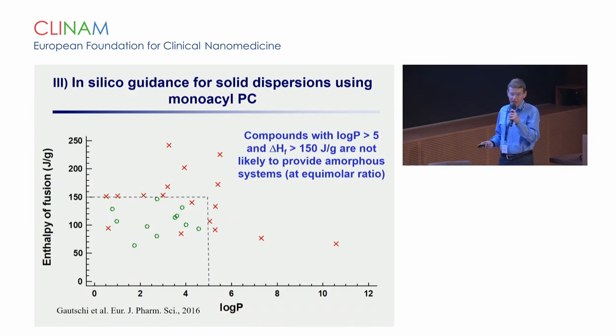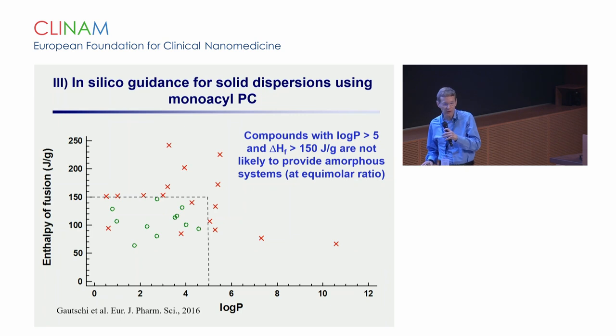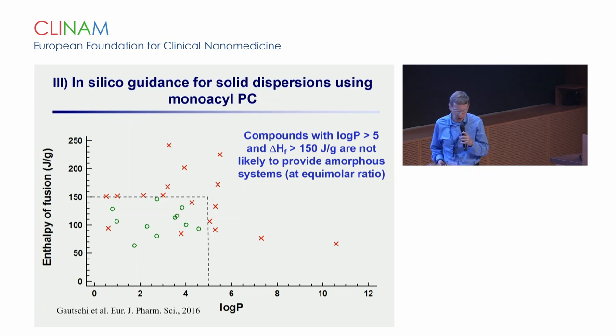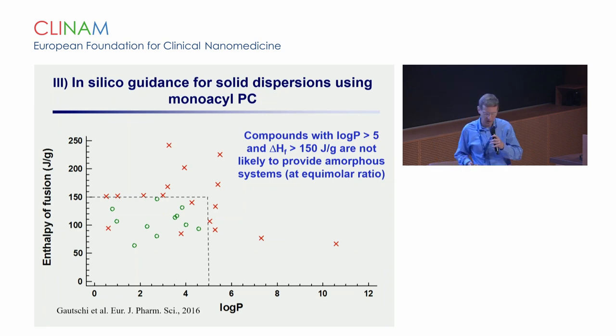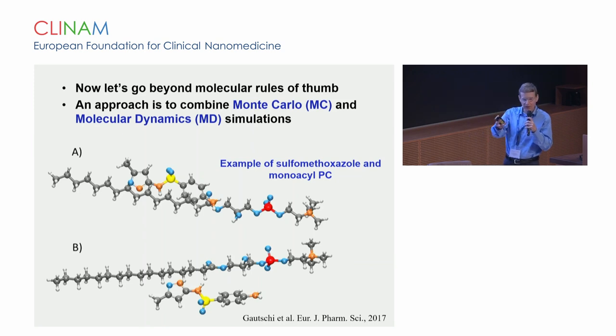We then did a discriminant analysis, looking at different physicochemical properties, and this worked quite well to differentiate which compounds form amorphous complexes as opposed to others that do not. When you plot the enthalpy of fusion against log P, you can actually separate the two types of systems.